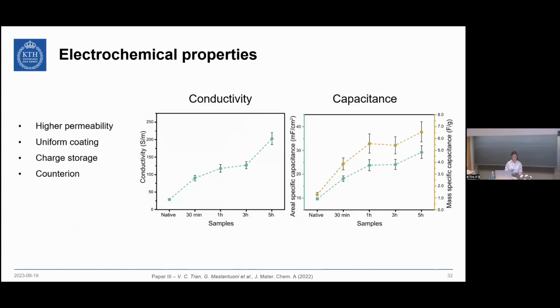So regarding the electrochemical properties, if we see what happens with the native wood infiltrated with PEDOT:PSS, then we could see actually an improvement of conductivity of 7 times the more we push sulfonation, as well as 3 times in the case of the capacitance. And the reason for this is that the permeability of the wood is higher, so we were able to introduce more conducting polymer. At the same time, as I just said, the coating was uniform inside the material, and this is argued to improve the electrochemical properties.